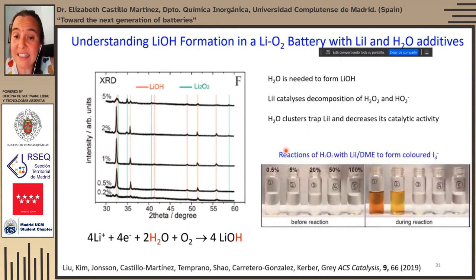This can be further seen in these photographs where different amounts of water were added to a solution of hydrogen peroxide, and some lithium iodide and DME were added. And when the amount of water was adequate, there was oxidation from the iodide to the triiodide, and therefore the solutions were colored.